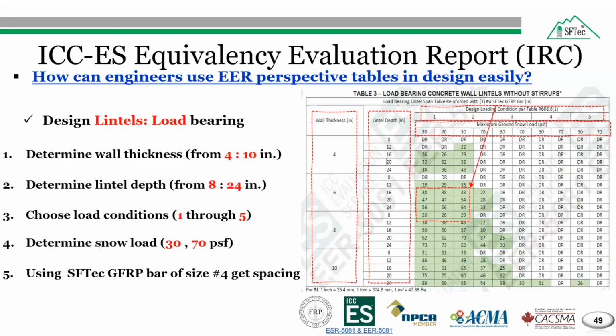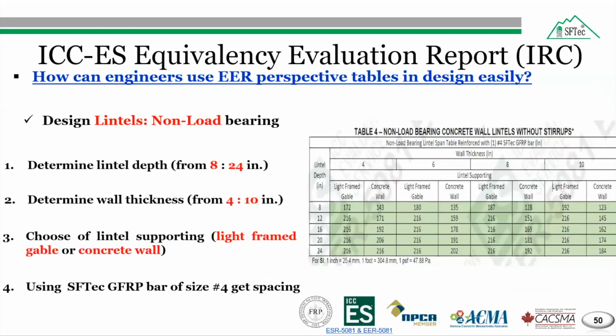number 4, get the spacing. Conversely, when designing lintels for non-load bearing purposes, number 1, determine lintel depths from 8 to 24 inch. Number 2, determine wall thickness from 4 to 10 inch. Number 3, choose the lintel supporting from light framed gable or concrete wall. Finally, using SFTec GFRP bar of size number 4, get the spacing.